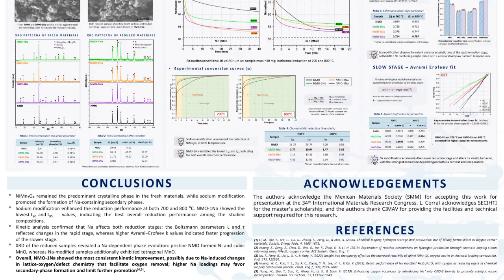Overall, the results indicate that a relatively low sodium loading can effectively promote the reduction of nickel-manganese oxide, potentially through changes in lattice oxygen and defect chemistry that facilitate oxygen removal. These findings provide useful information for tuning the reduction behavior of nickel-manganese spinel oxygen carriers for chemical looping applications.